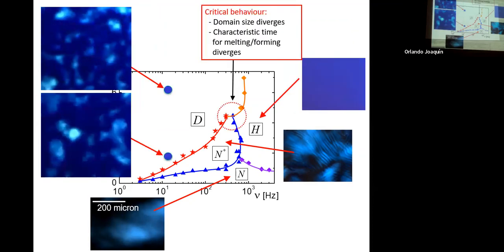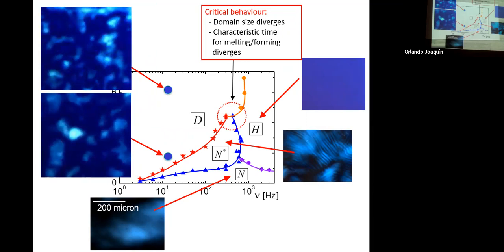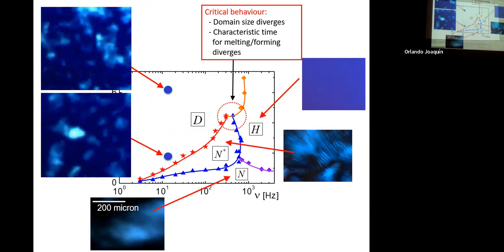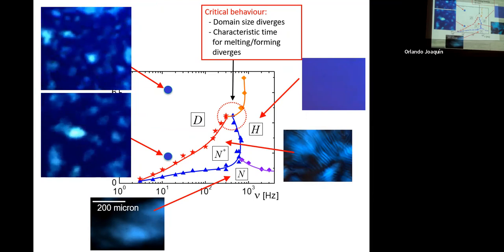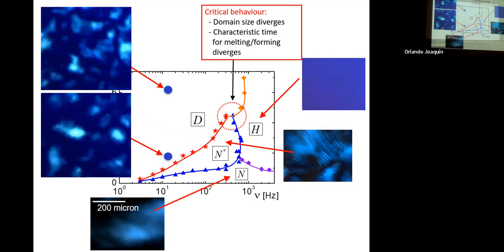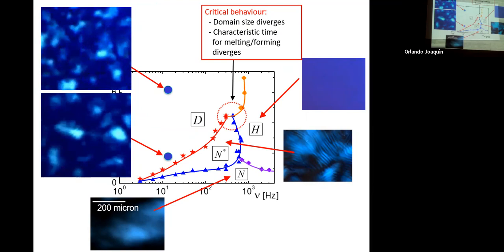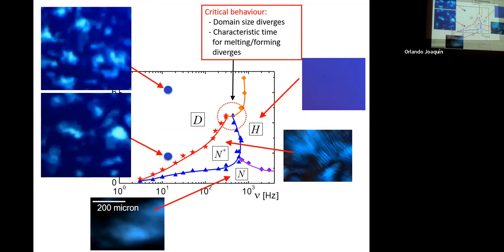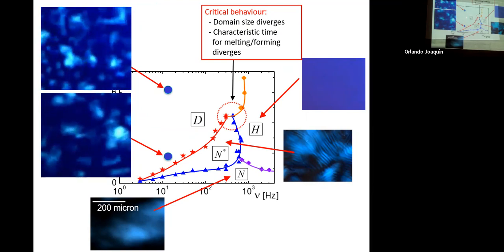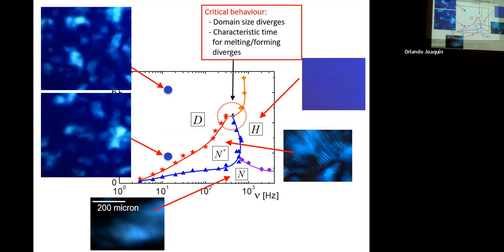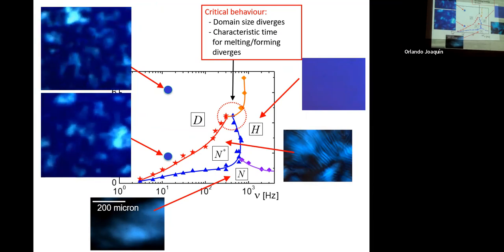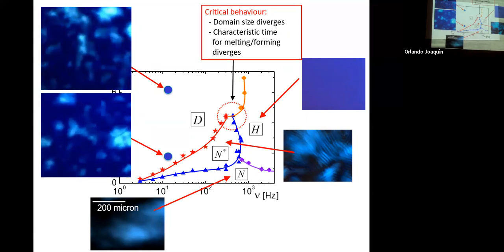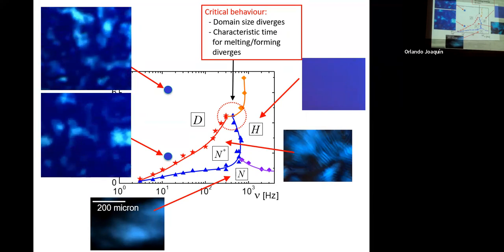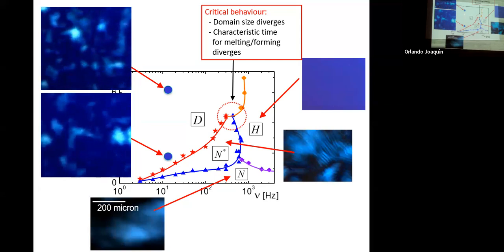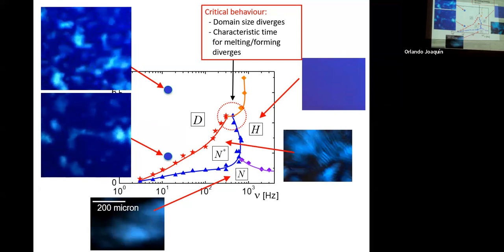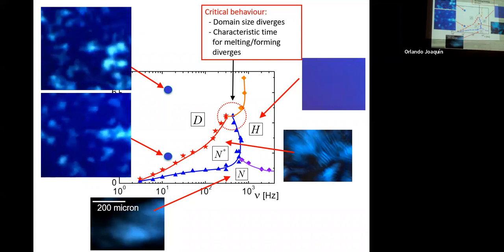And in fact, the time scale on which melting and reforming of the domains occurs has nothing to do with the frequency, but has to do with the distance from this transition line. So if the distance is large, the time scale is short - they melt and form very rapidly, and this is real-time, moving this one as well. You see as you approach this line, the dynamics becomes very, very slow.